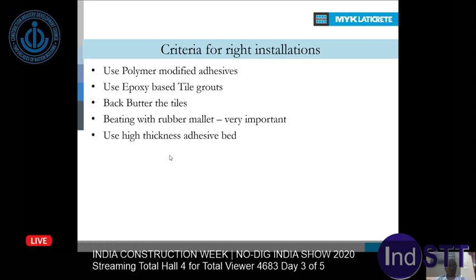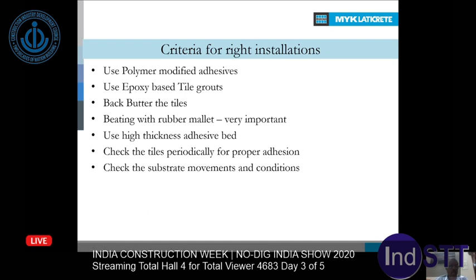And wherever you need, suppose you are using large format tiles, then it's highly recommended to go with a high thickness adhesive bed. They're all designed to withstand shrinkage and any kind of issues that come with the high thickness. Water shrinkage is very, very less. So again, 15 to 18 mm is the minimum thickness we recommend for large format tiles. And once done, make sure you check the tiles for proper adhesion immediately, so that if any area has a hollow sound, then take it off, reapply and refix the tiles.